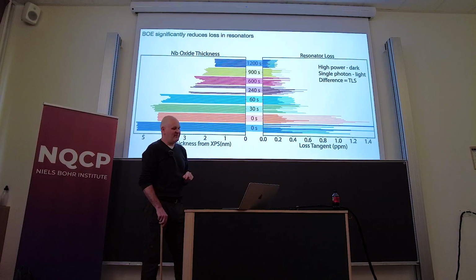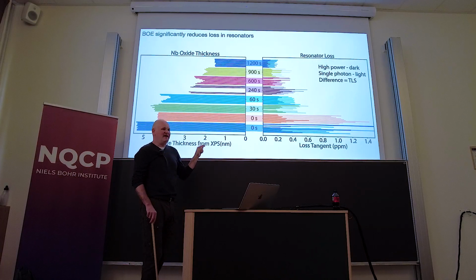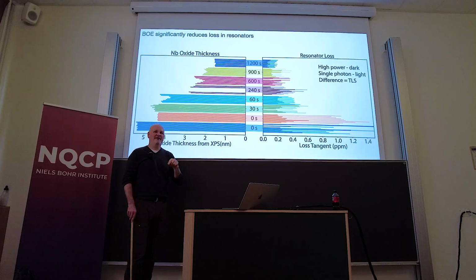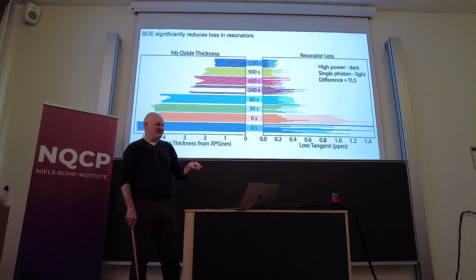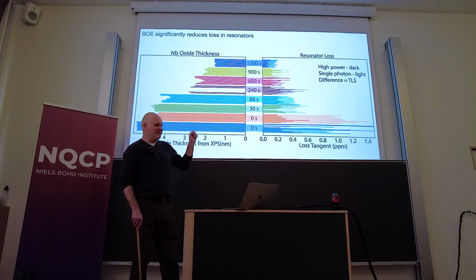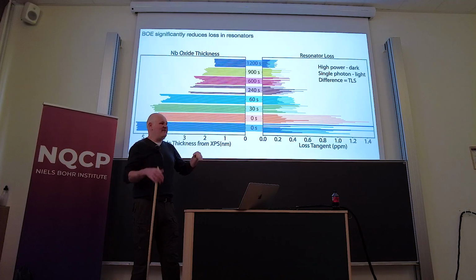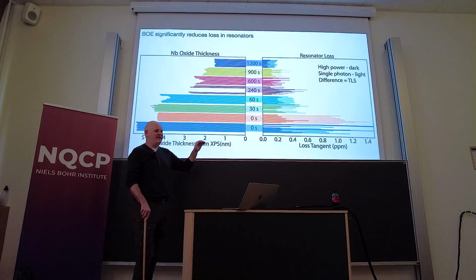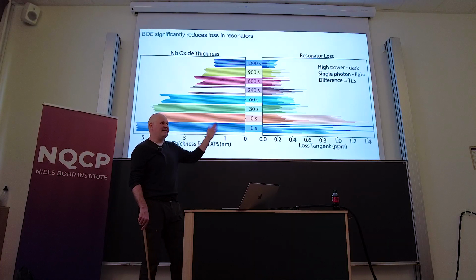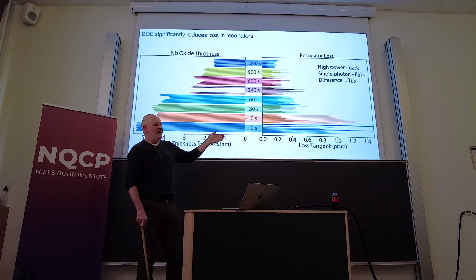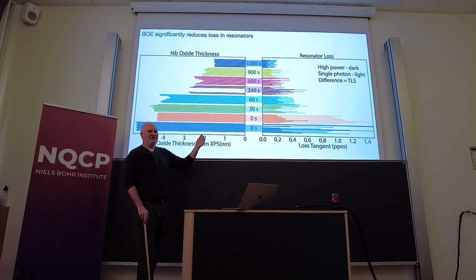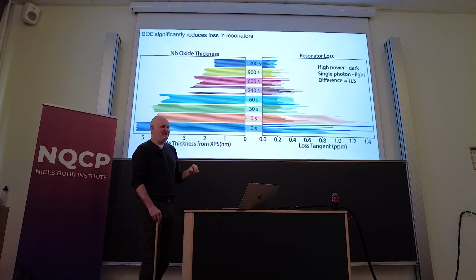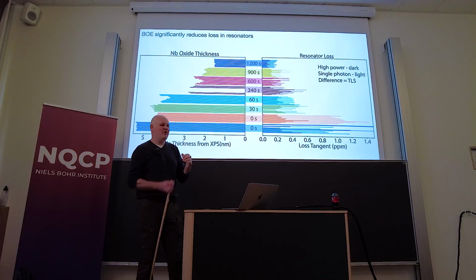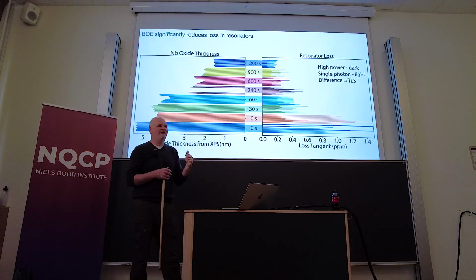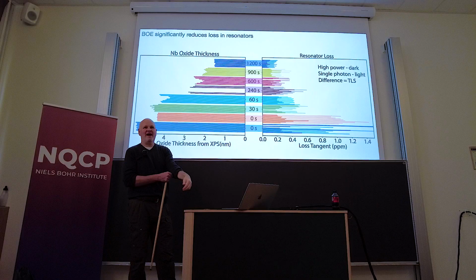But the most interesting thing, perhaps, is that there is a difference between the oxide that forms under plasma versus the oxide that forms in air. So if you take these devices and you dip them in buffered oxide etch and look at them before the oxide etch and after, even if you leave it out for a week or month, a year, it doesn't matter. The quality factor basically stays the same once it's been dipped. Whereas it's much, much worse after it's come out of the oxygen plasma. And it's some combination of probably thicker oxide, but then I think it's also more diversity in the species of niobium oxide that you get from this plasma because you're bombarding the surface with radical oxygen ions.